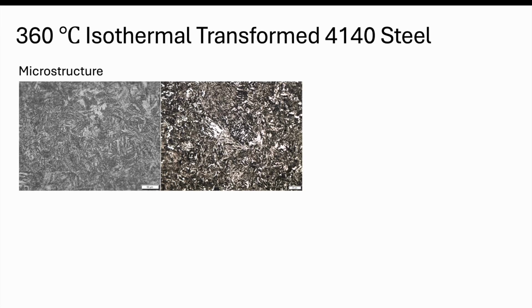Here is our microstructure. Again, two different images from different groups and different years. You might notice that this structure actually looks very similar to martensite. It can often be mistaken for martensite. This is just an optical microscope image, but if we were to zoom in, we would hope that we could see those very fine ferrite and cementite layers. Unlike martensite, which is a metastable phase and uniform throughout, bainite is a fine mixture. It's difficult to see the differences here, but this is in fact lower bainite. Bainite can be tricky without electron microscopy to really see the differences.